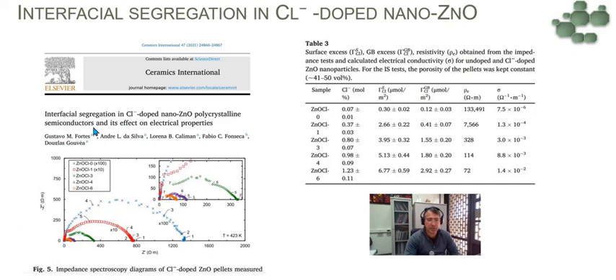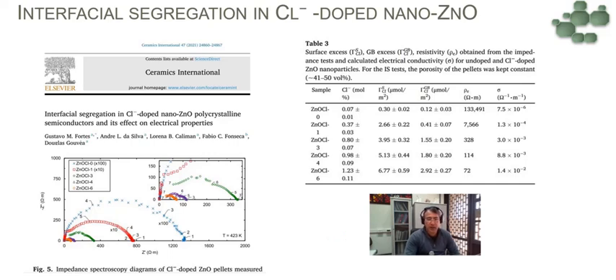In this impedance spectroscopy diagram, we can see that the increase of chlorine in zinc oxide decreases the total resistivity. You can see the total resistivity decreasing with chlorine, and consequently we have an increase of conductivity. This semicircle here is referred to the grain boundary resistance, and you have a strong decrease in the grain boundary resistivity. As a consequence, there is an increase of total conductivity. This is very important for having more time for electrons and holes without any recombination, and then increasing the photocatalysis.